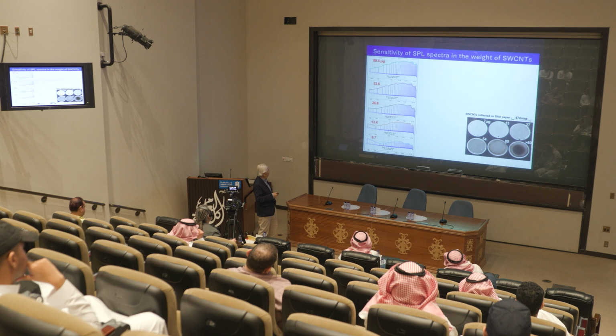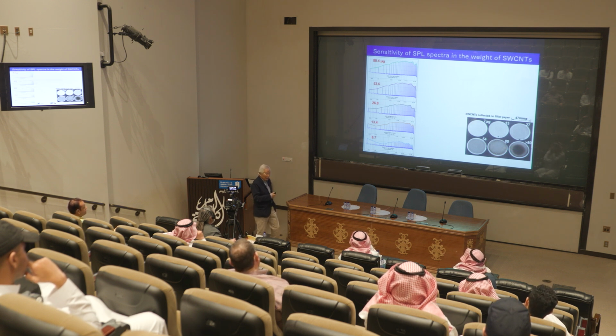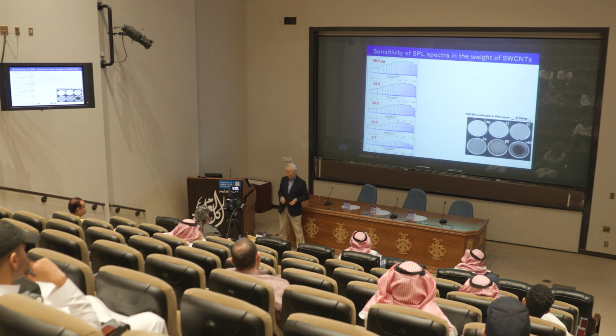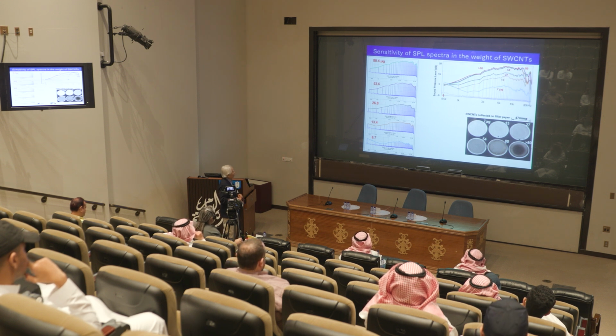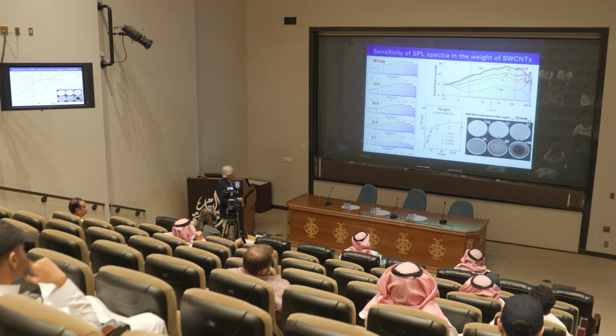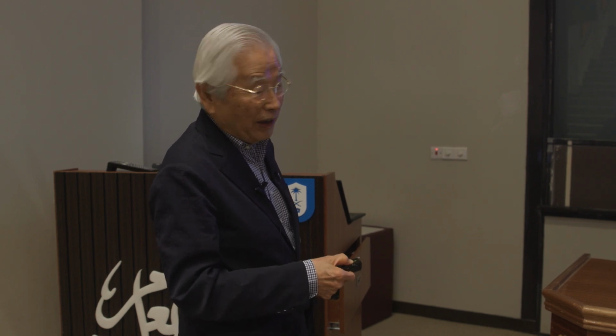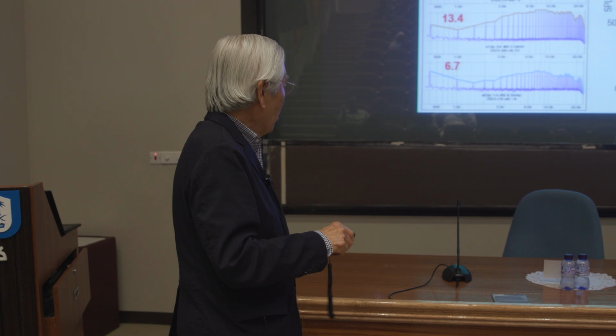papers. So this is the spectrum. 0.77 is this. And as you increase the amount of the material, carbon nanotube, you can hear more sound. So this is sort of related to the weight of our nanomaterial. So in that way, we can measure the weight. All right. So now another one, you can plot like that. This is weight, and this is the strength of sound. So as you increase the weight, the sound gets bigger and bigger. And at some stage it saturates. If it's too dark, then it's saturated. So in this region, you can measure very small amounts.